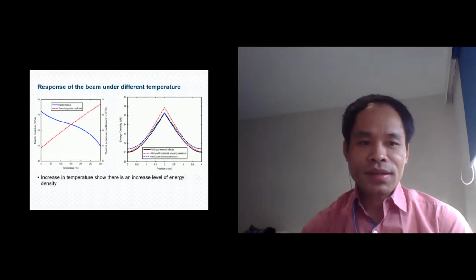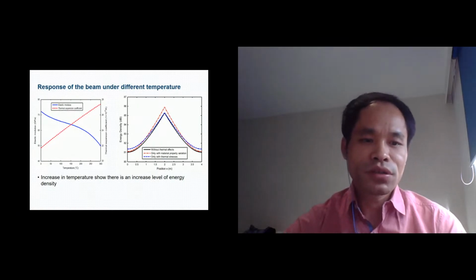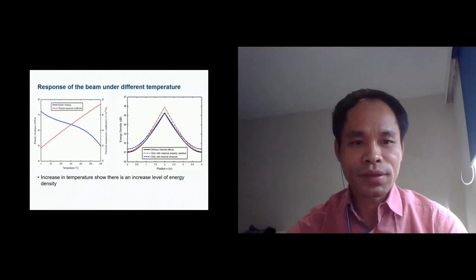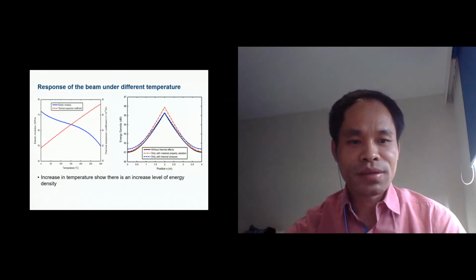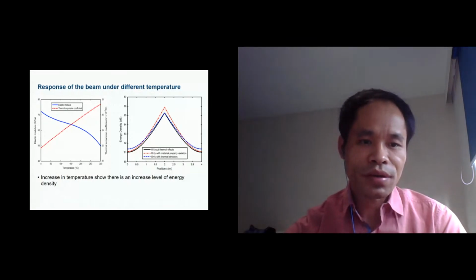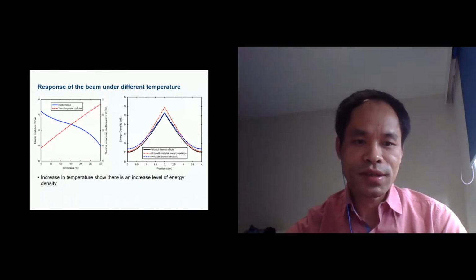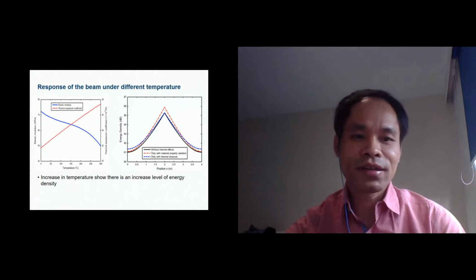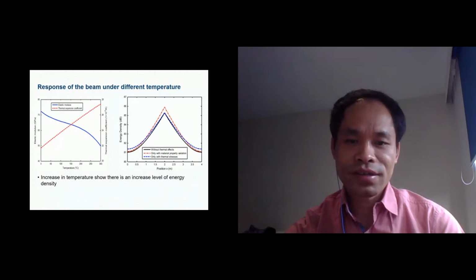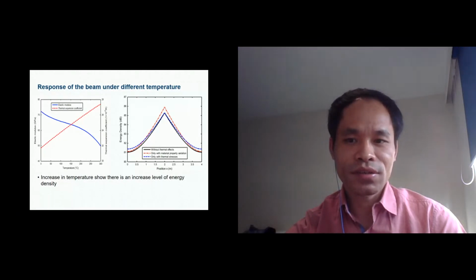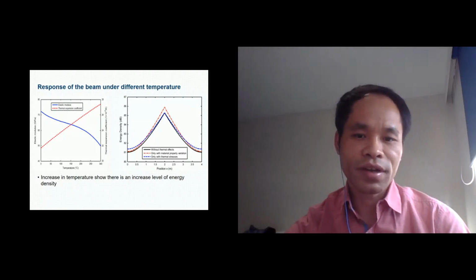Now, regarding the response of the beam under different temperatures, some other people have also done research, because temperature has an impact on thermal properties. This research shows that when you increase the temperature, Young's modulus or elastic modulus decreases, but thermal expansion increases, which is related to strain. So when you increase or decrease the temperature, the material properties change, and this indirectly affects crack initiation. In this graph, with and without heat conduction thermal effect, the deformations keep changing. This shows the importance of considering temperature for crack evaluation.